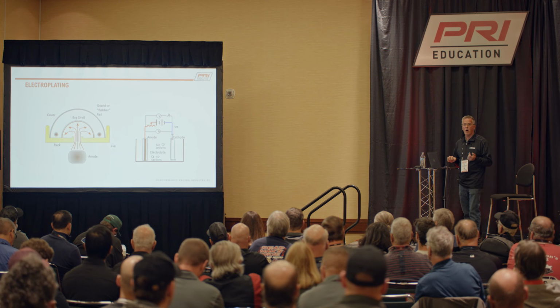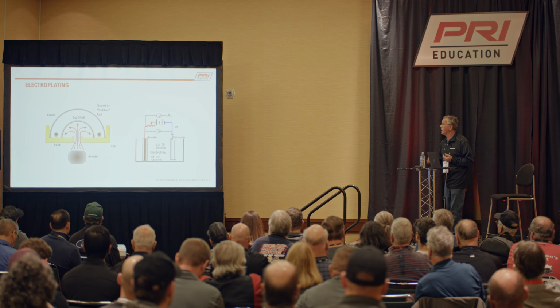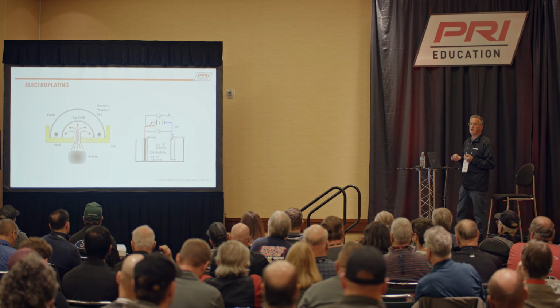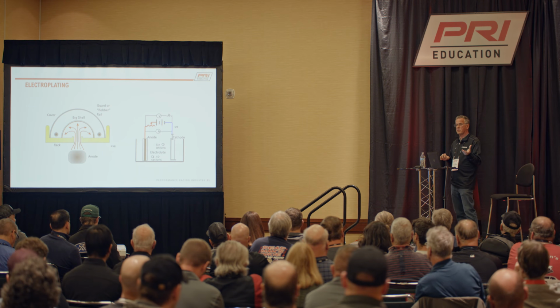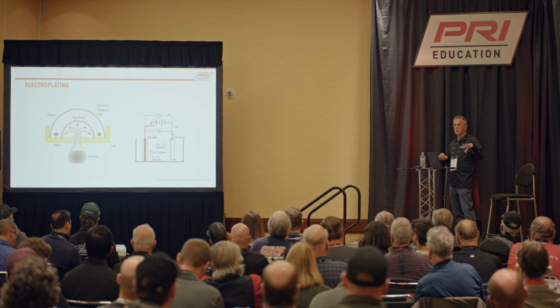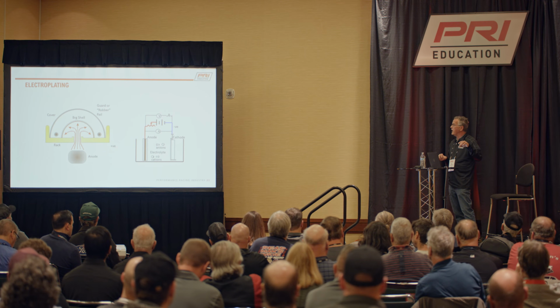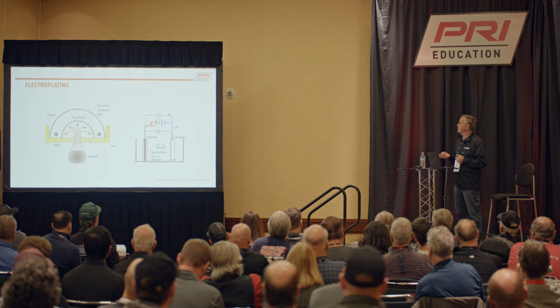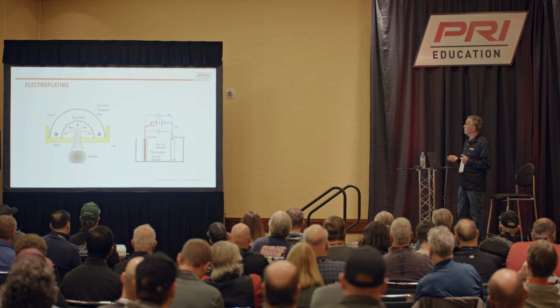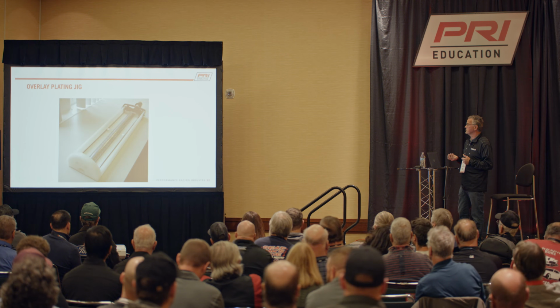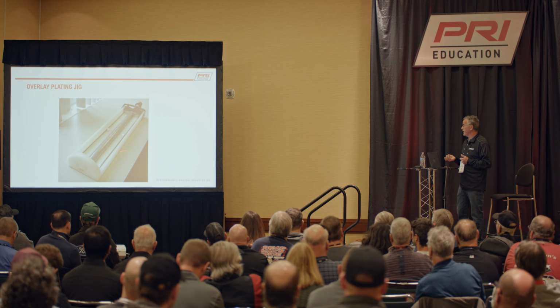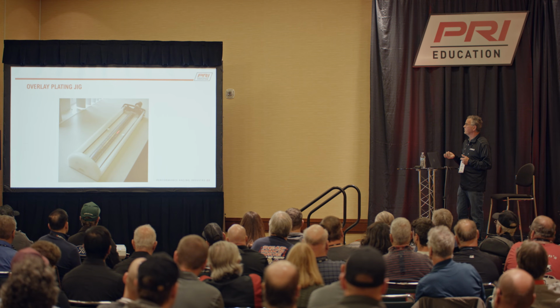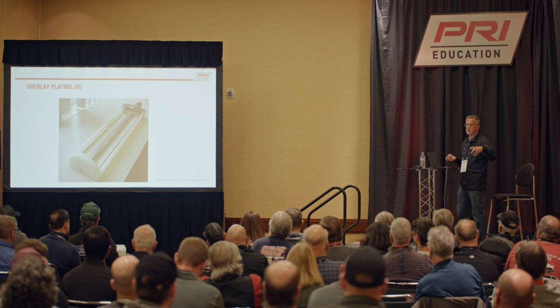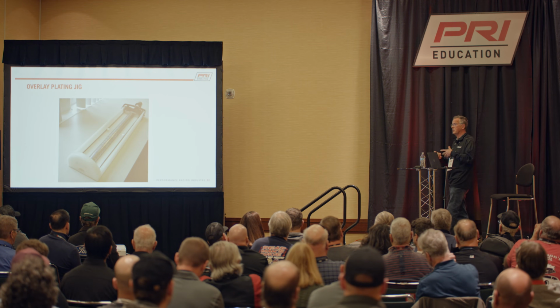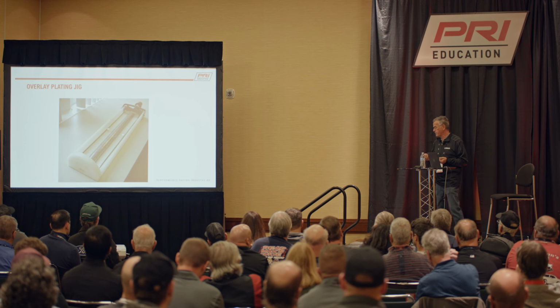So all the overlays, it's electroplating. I'm not going to get into that too much, but the bearing starts out with a piece of steel with bronze on it, and it's machined, and then the overlay is electroplated. So it's basically how that works. There's a tooling. You lay in a production run. This would be part of it. You put it in there. It's dipped, electrodes, it electroplates it, and that's what you see.